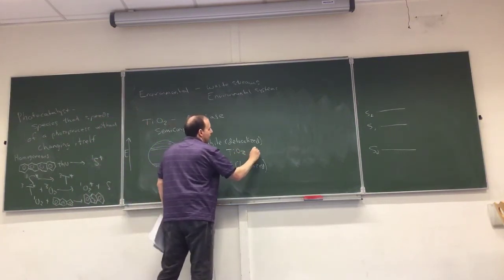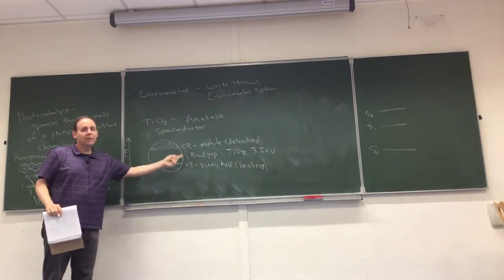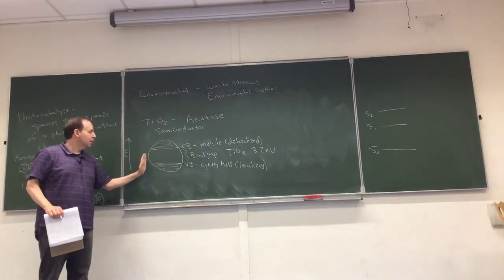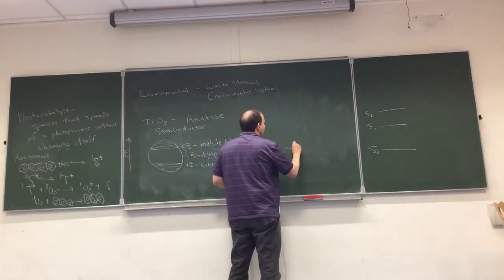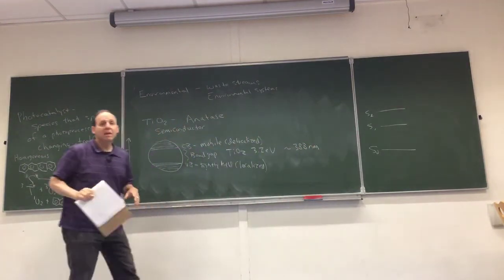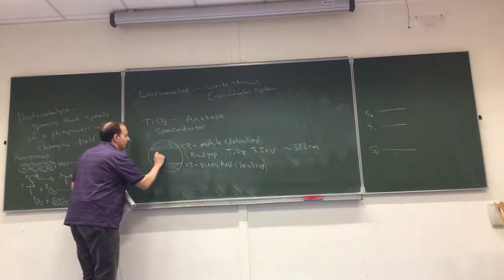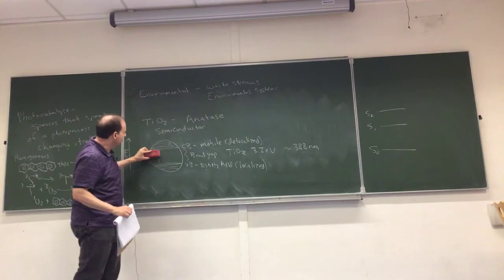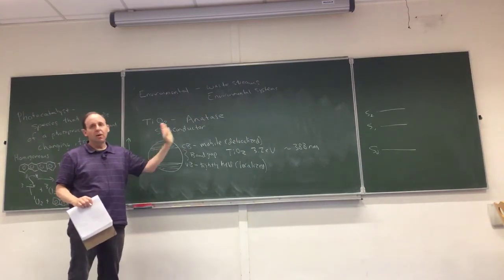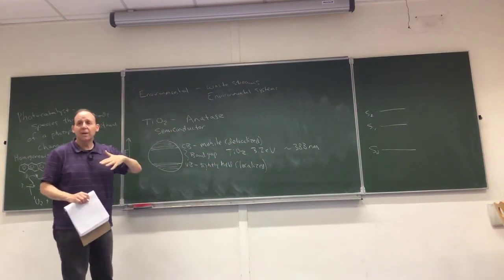The band gap is the difference between the top of the valence band and the bottom of the conduction band. For TiO2, that gap is about 3.2 electron volts, corresponding to approximately 388 nanometers. If you irradiate TiO2 with 450 nm light, that photon doesn't have a corresponding energy level to be absorbed — there's no energy level there, so no absorbance occurs. Anything longer than 388 nm won't be absorbed; anything shorter will be absorbed.